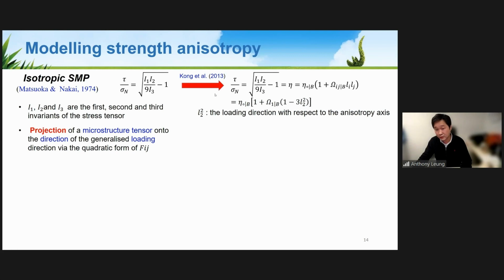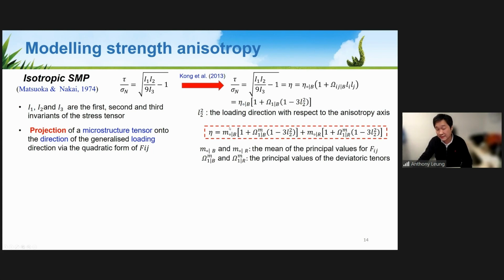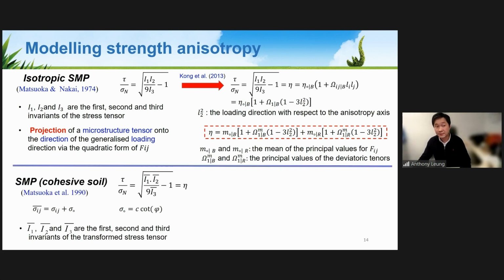So we can further break it down using the previous matrix I showed you like this. So what we did further here is to propose another anisotropic parameter for rooted soil. So if you compare those two equations, I have another additional term there to describe the effects of the root network. Okay, so with this anisotropic parameter, we can then capture the anisotropy in this SMP model. Okay. However, as I showed you earlier, the rooted soil is cohesive. Now, this Matsuoka and Nakai failure criterion is for frictional material without any cohesion. It couldn't perfectly model our rooted soil because it is cohesive, especially in the extension path.